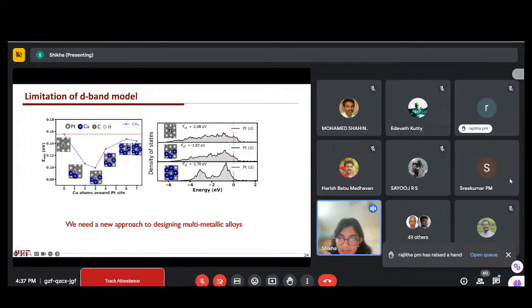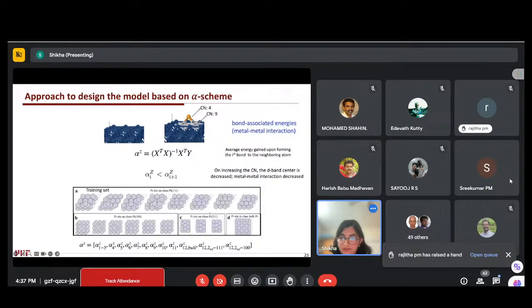So we have to take into account the width of the D states. Therefore, we aim to design a new approach to predict the activity of the alloy surfaces, and the idea is that we want to perform only limited DFT calculations to design our model. And the model is based on the alpha scheme. So what is alpha? Alpha is the bond associated energy term, the interaction between the metals. So what we will do is predict the bond energy with our model.